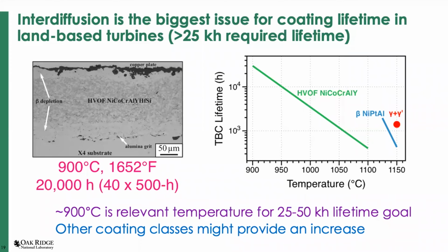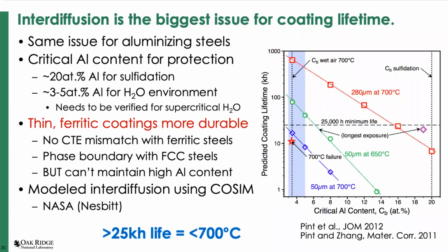So again, 900 degrees C doesn't sound very high, but that's about where a lot of land-based gas turbines are operating. Now that's the metal temperature. So you've got a higher temperature at the surface because you've got a thermal barrier coating on top of that. And you might be able to improve it a little bit with other coating classes, but these days the industry is mainly using these MCrAlY type coatings. And again, I'll make the same point again. Interdiffusion is the biggest issue for coating lifetime.